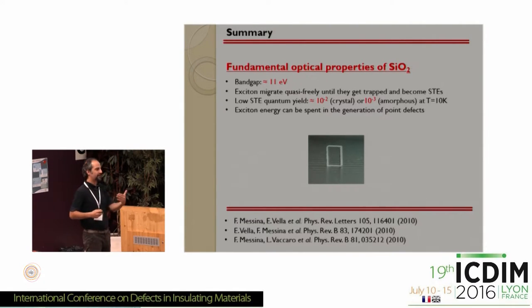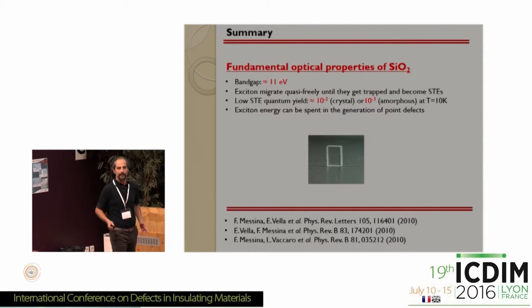But after a certain time from the initial generation, they can either get trapped somewhere and become self-trapped excitons, but they can also give rise to different outcomes. One of these is the generation of point defects, as evidenced by their luminescent signals.